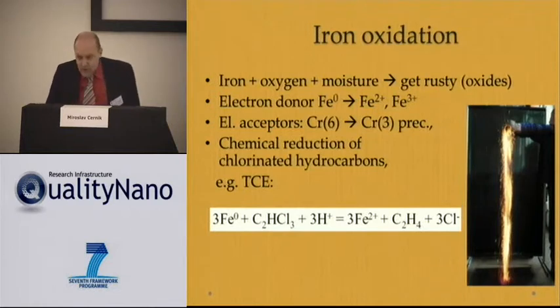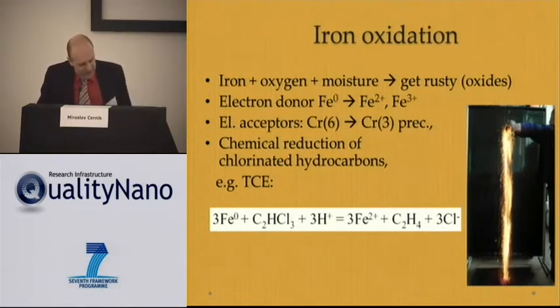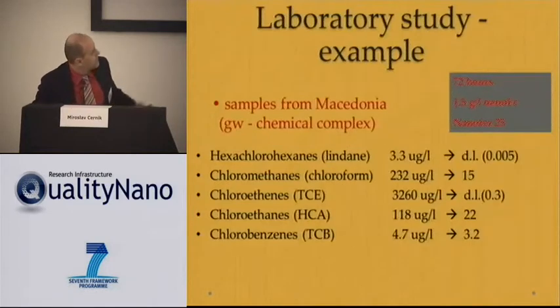The iron nanoparticles are so reactive, as you see on the picture, that of course they react with the oxygen in fire. And our task is to use these particles, to somehow change them to be able to treat the contaminants like the chlorinated hydrocarbons here. The trichloroethylene is changed by the reaction with iron to ethene, which is, of course, not dangerous, not so toxic like the original chlorinated hydrocarbons.